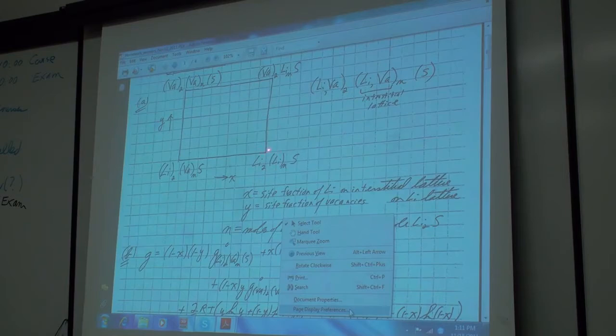And in this case, this G0 minus this G0 is the Gibbs energy of putting lithium ions into the interstitial site. So that's a real parameter. And this G0 minus this G0 is the Gibbs energy of putting vacancies on the lithium sites, and that's a real model parameter too. Remember, you never ever get over here. You're only talking about a small region here.